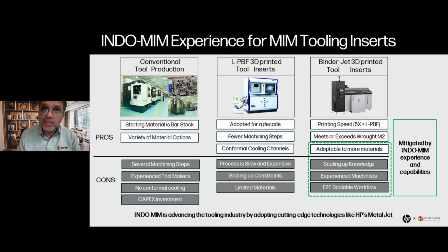It was a great switchover from conventional machining to 3D printing. We were able to significantly improve our productivity. But the problem with LPBF was that it was still a very slow process compared to binder jet, and scaling up was a major issue. Also, there were not many materials available through the LPBF route. Most of us used only maraging steel with only 55 HRC hardness, which was not good enough for a lot of tooling applications.